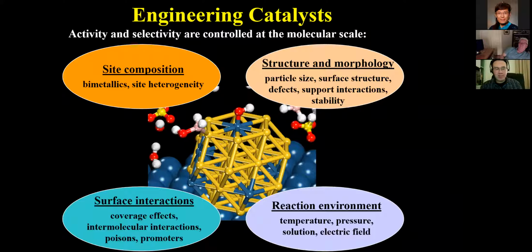And activity and selectivity are affected by the properties I show here, which all can boil down to molecular level phenomena that dictate our catalyst activity and selectivity: whether or not it's what we make our catalyst out of, the site composition. For instance, I show a bimetallic where we can change the arrangement of two different types of metal atoms in order to try and facilitate our chemistry. The structure: whether or not we're on a flat surface, an edge, if we're interacting with a support underneath. Other molecules, other species in an electrocatalytic environment, maybe the electrolyte, ions present in the electrolyte solvent can alter the stability of species at the surface, and the reaction environment itself all translate down to the molecular level to affect the energy involved in breaking and forming bonds.